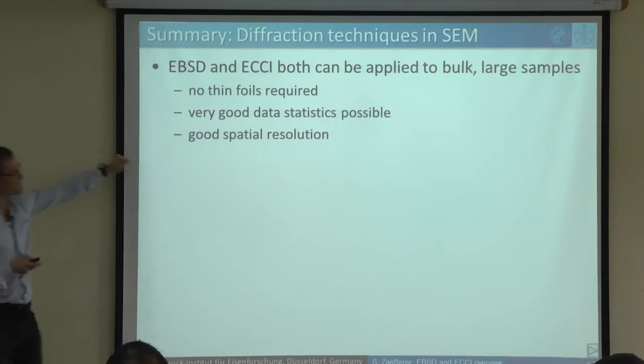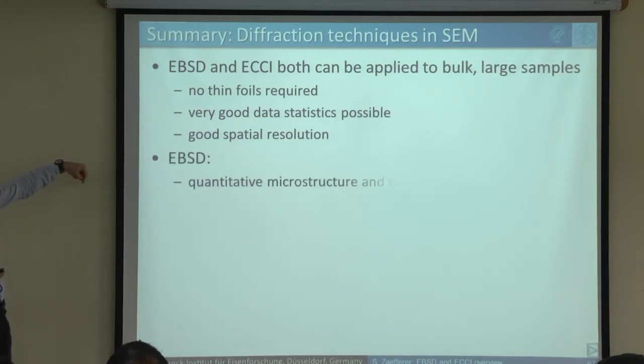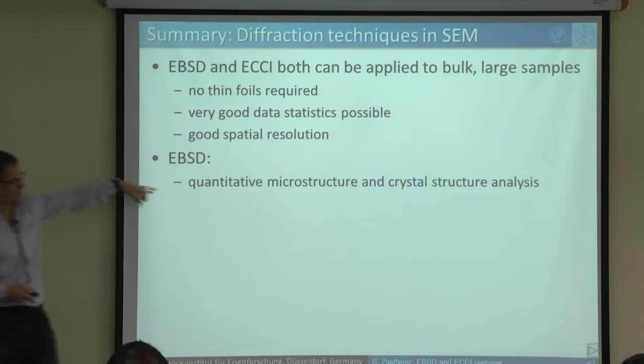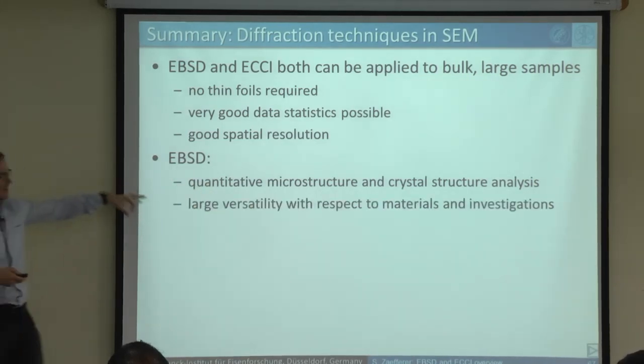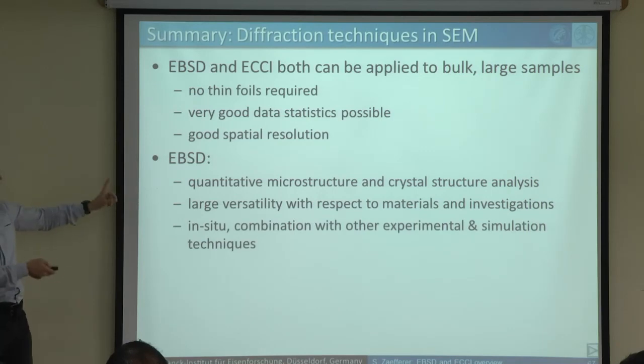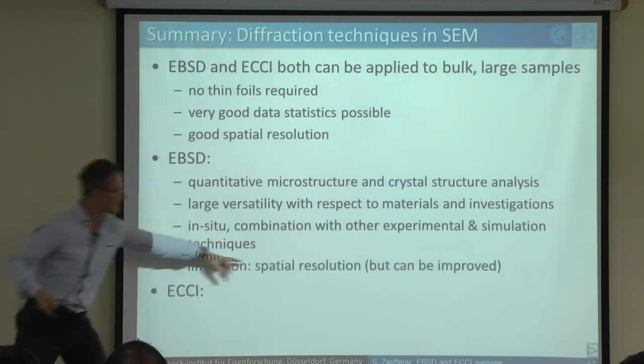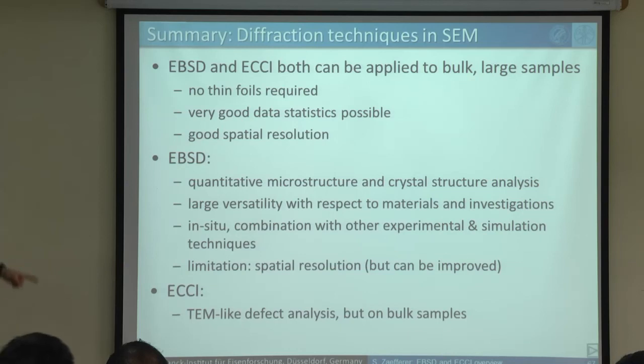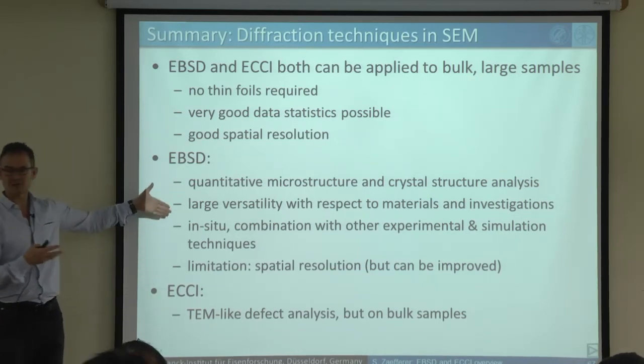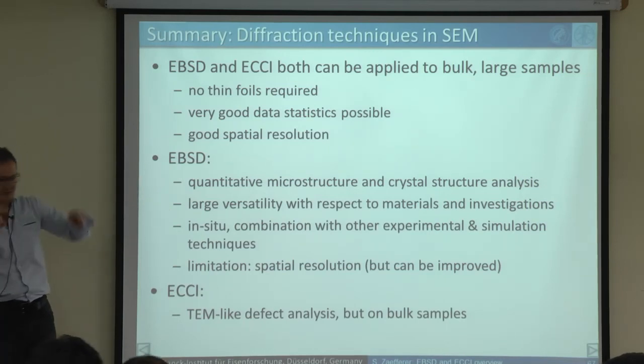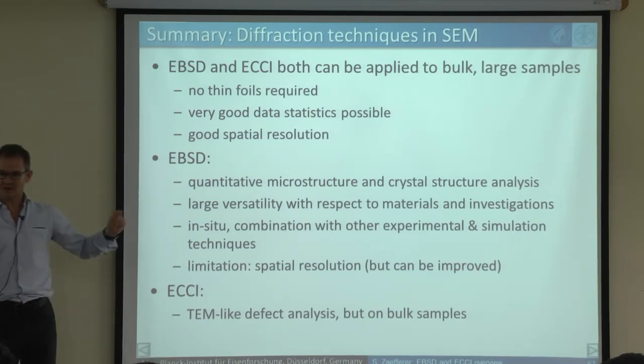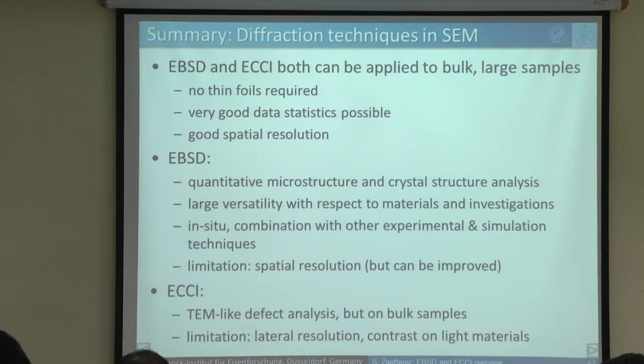You get, nevertheless, reasonably good spatial resolution. With EBSD, we have spoken, quantitative microstructure, large areas, in situ possible, and so on. Limitations, I mentioned, spatial resolution. And with ECCI, as a complementarity, you can see here you see the defects only indirectly, by rotations. Here you see the defects really directly, like you do it in TEM. And again, with respect to TEM, lateral resolution is, of course, a limiting factor.